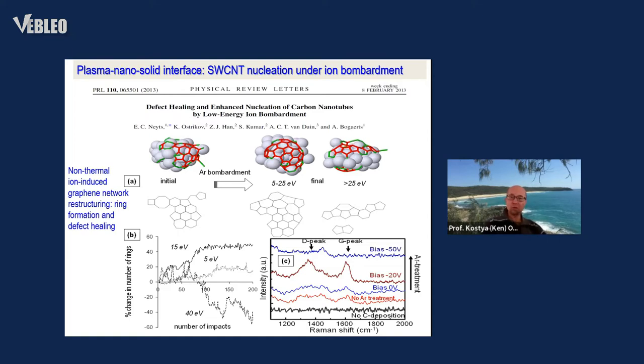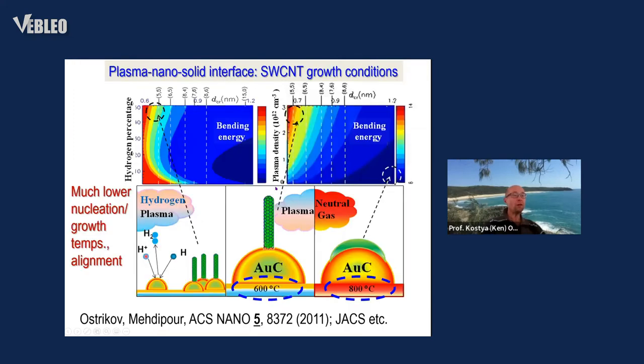And this work proves that if the energy of argon ions is in the range from 5 to 25 electron volts, then not only is the developing carbon network not damaged, but it also is restructured. Hexagonal rings are formed, and the defects are healed. From that small graphene cluster, the carbon nanotubes form. They form in a way that the cluster, the first layers of graphene, bend, and then they are extended and form carbon nanotubes.